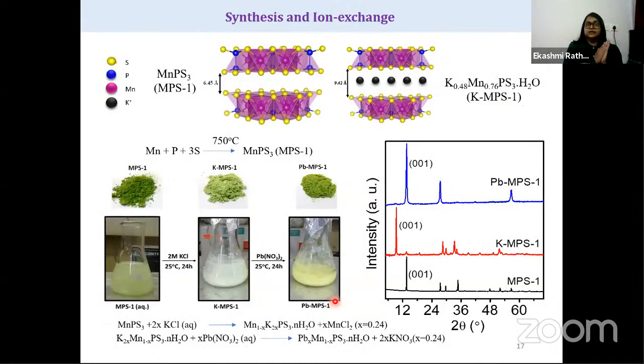I designed a layered metal sulfide called MnPS3. These are the P2S6 units sandwiched by the Mn2+ ions, and the layer spacing is 6.45. To improve the efficiency of this material, I intercalated potassium so that the layer spacing increases, and it helps to capture lead efficiently.